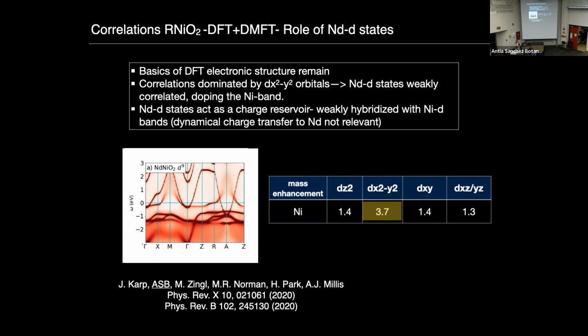So what we find in DFT plus DMFT is that the basics of the electronic structure that I just showed you remain. You can see that here in the spectral function, other than, of course, for renormalization effects. The correlations, importantly, are dominated by the dx square minus y square orbital. That's a pretty cuprate-like scenario. What we find is that the neodymium D states are weakly correlated. They simply act as a charge reservoir, but they don't have a much more active role in the electronic structure of the material. And this was quite important at the time because people were trying to decide whether those neodymium D states actually had a deeper role or not. As I'll show you in a few slides, this picture is actually consistent with what you find in the other superconducting member, that is the 5-layer material.